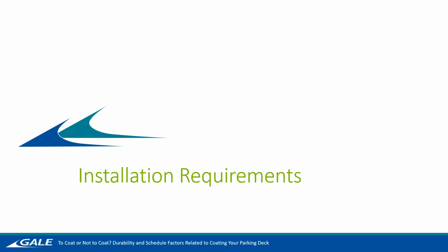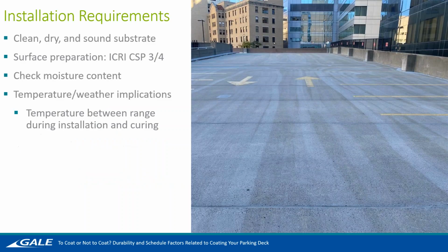So now we're going to installation requirements. Now that we've selected our traffic coating, what are we doing to make sure that it's installed properly? You're going to want a clean, dry, and sound substrate. As I said before, with the sound substrate, you're going to want to make sure that a condition assessment is done and all of the existing defects are repaired. You don't want to install a traffic coating over it and then immediately breaches are created because of a crack, because of a spall, because of delamination. You want to make sure that none of that's going to happen and you're starting on a clean, fresh surface.